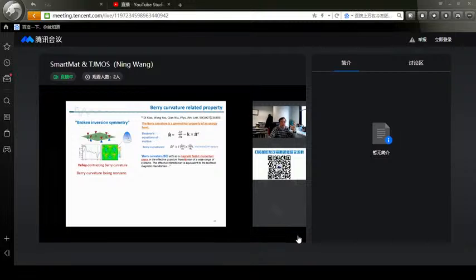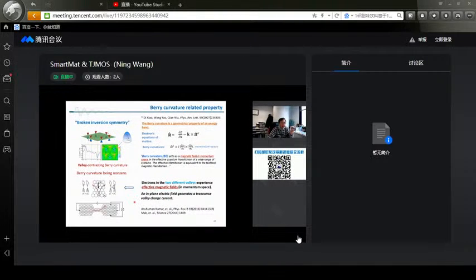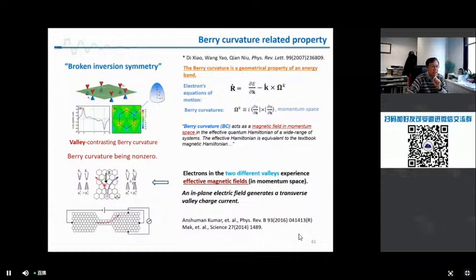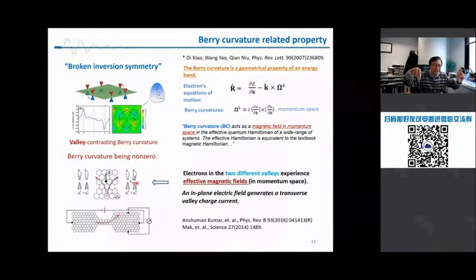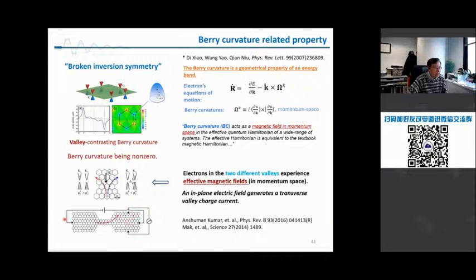So you can imagine that if there's magnetic field, we call this pseudo magnetic field, then the electron behaviors will be changed, like Hall effect. And indeed, previously we have studied the so-called valley Hall effect. What does it mean? That means in this inversion symmetry breaking system, there's strong Berry curvature, and the electrons at different valleys feel different forces in momentum space. So that's an effective magnetic field. And this spin up, spin down is from different valleys, as I introduced. So those two kinds of electrons will go in opposite ways and accumulate voltage. Once you detect the measured Hall voltage and divide by the current you injected, that is called resistivity or conductivity. All right, so this is the principle.